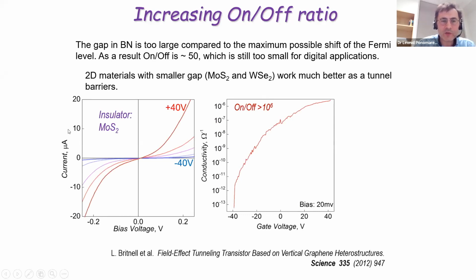IV curves: current versus voltage between source and drain, what's called bias voltage, at different gate voltages. If we look at the slopes of these curves around zero voltage, they simply give us the conductance, which we can recalculate into conductivity. Now if we plot this slope as a function of the gate voltage, we have the curve shown on the right. You can see this is a logarithmic scale. The conductivity changes a lot, and that means the on-off ratio is also very high. If we look at this part as the on state, and somewhere here, when conductivity is very low, as the off state, then this ratio will be at least 6 orders of magnitude, more than enough for transistors to be used in digital applications.